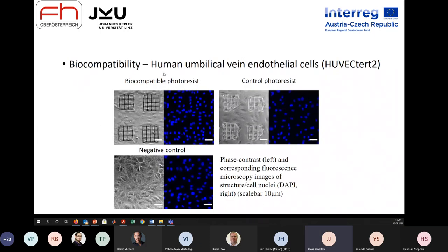Then we were playing with the photopolymers. We were checking the biocompatibility. First we used human umbilical vein endothelial cells for biocompatibility testing. The cells, as you can see, these are the nuclei of the cells growing on top of the structures, were nicely covering everything. On control photoresist, the density of the cells was lower. They were doing fine. They were not dying faster, but they were not growing as fast as on the biocompatible polymer. In our case, the biocompatible polymer was a methacrylate based type of polymer which was quite hard. It was in the megapascal elasticity range in this case.